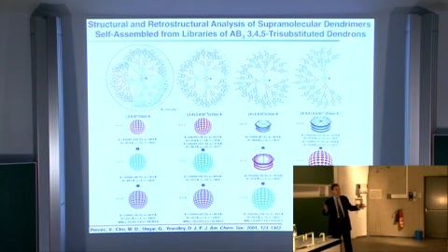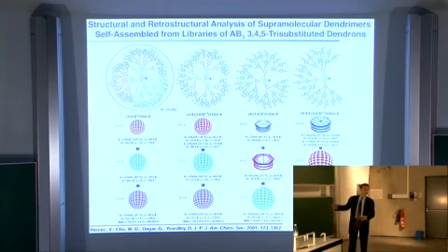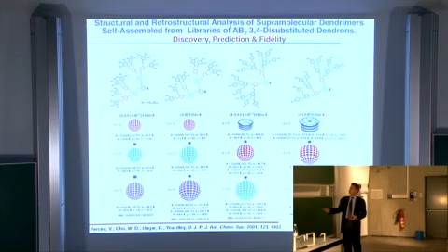And in the first instance, when we do very fast X-ray diffraction analysis, we do not know what's inside of this globular object. We know the conformation of the molecule, but we do not know whether that's a micellar-like structure with full freedom of the molecule to move, or it's a different structure that may resemble a protein. We go to the last set of molecules, and you see here a rod-like structure and the globular objects. Now let's change the inner part of the molecule from this library, from a 3-4-5 to a 3-4 building block. And you see that identical, identical. This became globular rather than rod-like. This is rod-like, this is globular.